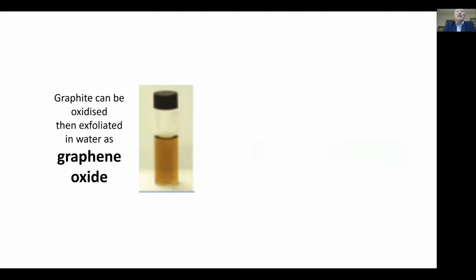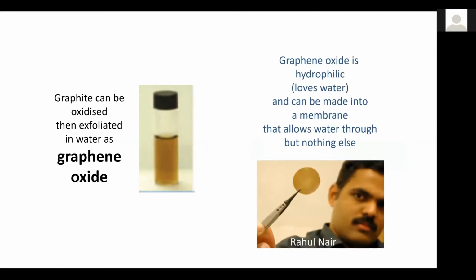Graphite can actually be oxidized to something that can be exfoliated in water, something that's referred to as graphene oxide. And graphene oxide is interesting in itself. It loves water, and actually it can be made into a membrane. This isn't a single sheet, it's actually layers of graphene oxide flakes, but that type of membrane is surprisingly, extraordinarily permeable to water, but when it's dry, it doesn't let anything else through. And that as well is something that's really interesting and something that we're making use of.